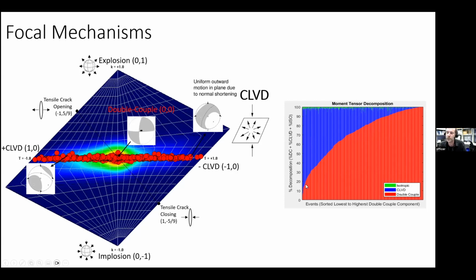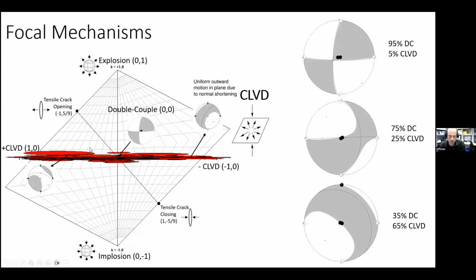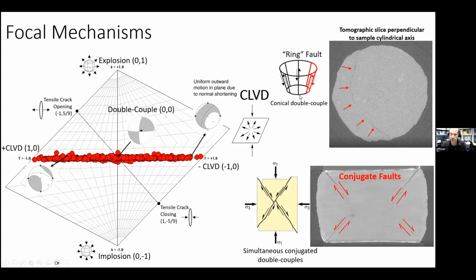But if you look at this plot on the right, this is basically showing you about two thirds of it is pure double couple, and then you have some of this CLVD component. But the CLVD, these are the error ellipses for the data I was showing. We have very good resolution of whether or not it would be an explosion or an implosion, but we have very poor resolution in terms of the CLVD components, because depending on the orientation of a shear fracture with respect to where the transducers are in space, it can become impossible to distinguish between this situation and this situation, which is why we have large CLVD components, but it's also why they have such large uncertainties. So I'm alleging that we have entirely shear fractures in our experiments, which is completely different to low pressure brittle failure.